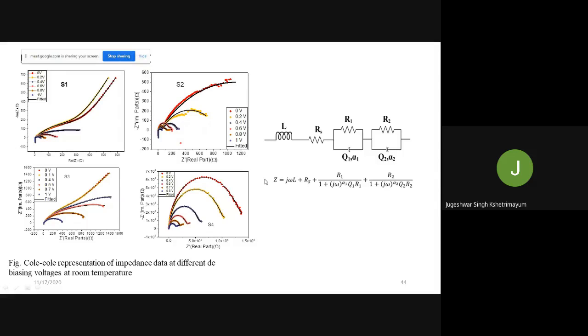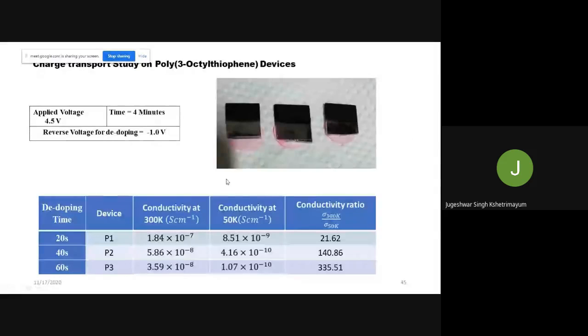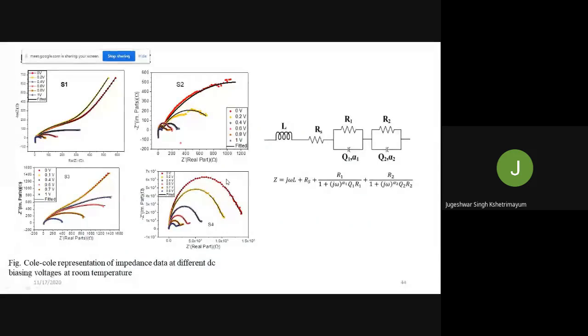Okay, so this is the pattern we plotted here, and we found a similar pattern. The results we put here are, say, the L in this case is coming from the connecting wires. Then here the RS is nothing but the contact resistance of the SS electrode.